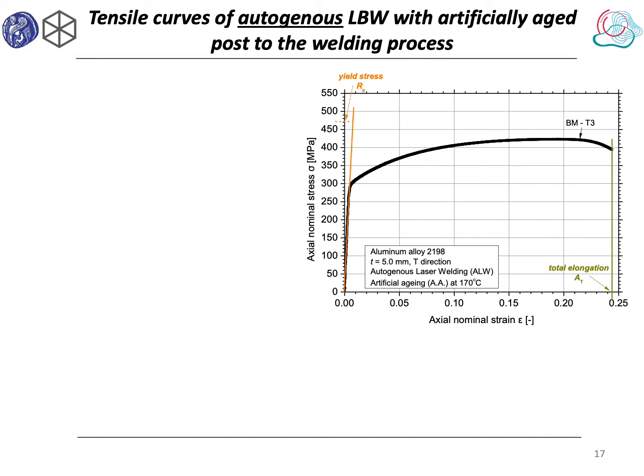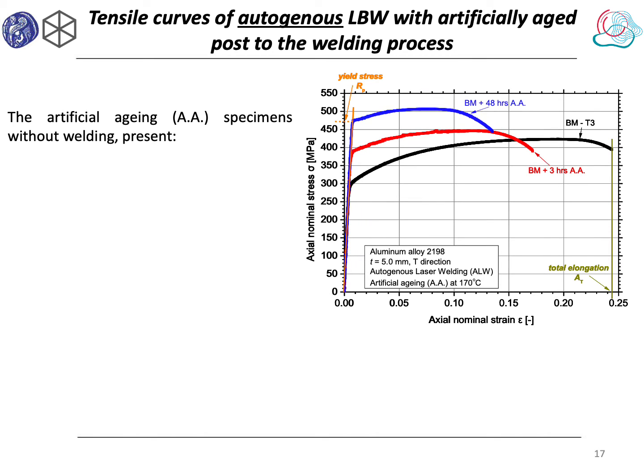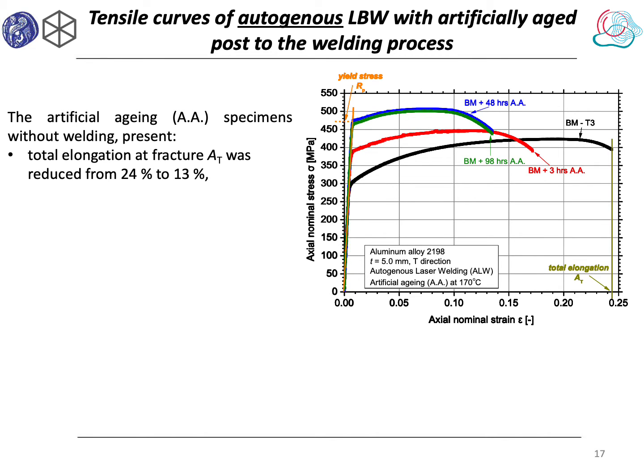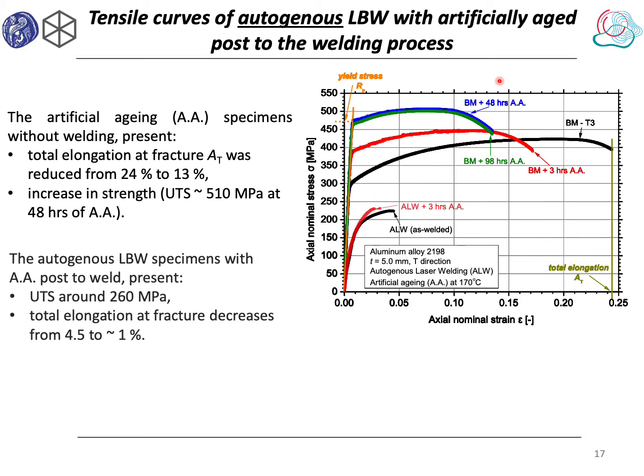For the tensile stress-strain curves of the base material, with increasing aging time, total elongation at fracture reduces from 24% to 13%, while strength increases up to 48 hours and peak aging condition. For autogenous welds, with increasing aging time, ultimate tensile strength increases up to 260 MPa, while total elongation at fracture decreases from 4.5% to approximately 1%.